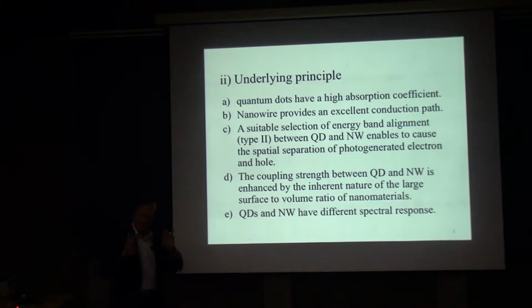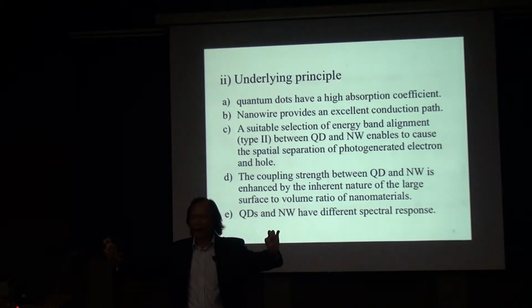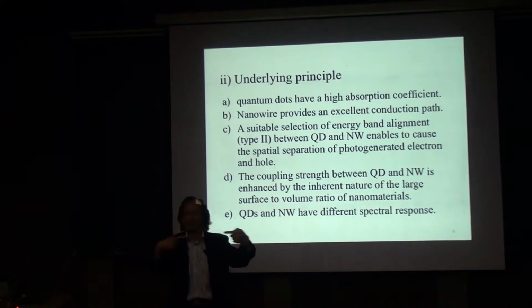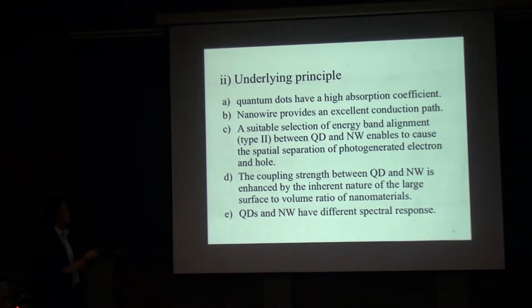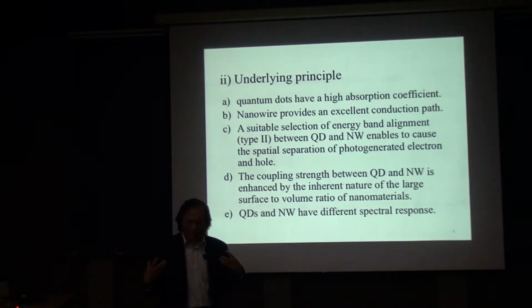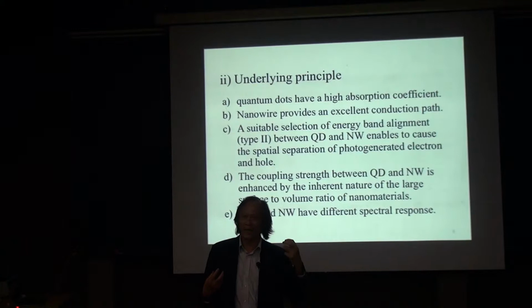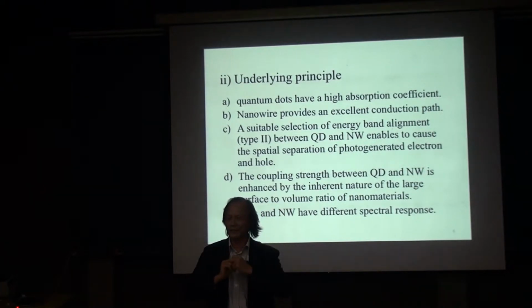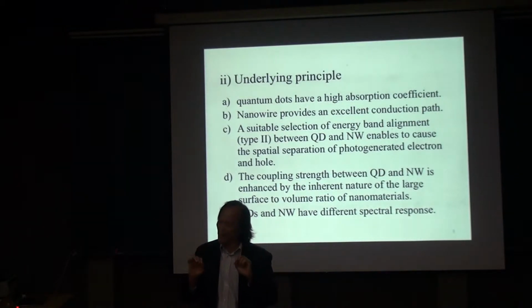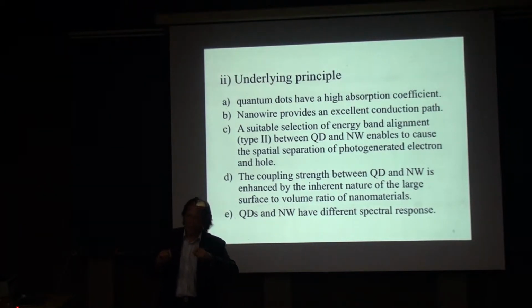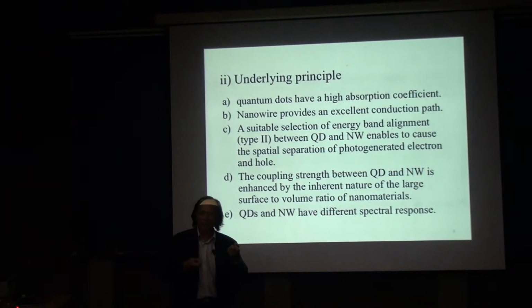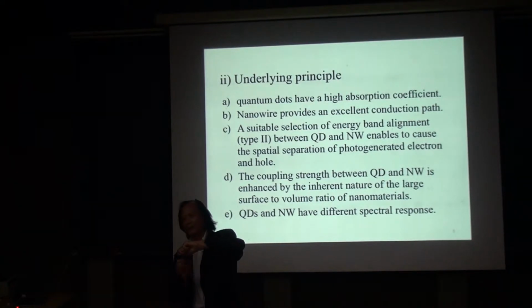Then the second point is that a single nanowire can provide a very good conducting path. That's very easy to understand, because electrons can easily pass through along the axis. So the main point here is that I have one material with a very high absorption coefficient, and one material that provides a very good conducting path. If I put these two together, you can imagine I can have an ultra high sensitivity photoconductive material. The main problem is, after the electron has been excited inside the quantum dot, how can it move into the nanowire and make the conduction?